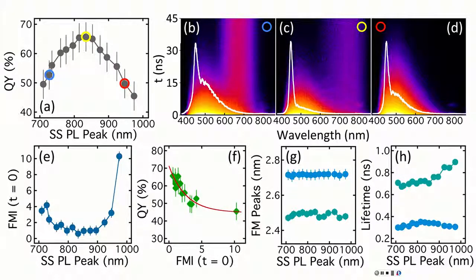And then this peak gets big as you go to the higher fractions, which are going to have more defects in. Technically, we can imagine that when you cut it from the crystal, there would be some edges, right? And maybe this would be really the state associated with the edge. When you change the size of the crystal, you still will have surface 111 meeting surface 110 or something like this, so you will have the same edge. And maybe that's why it's not shifting in energy.